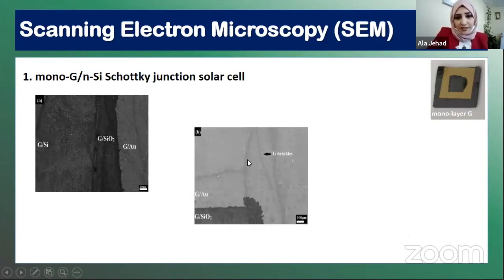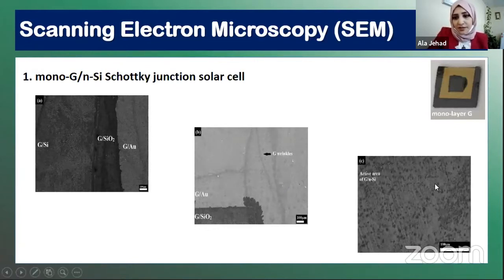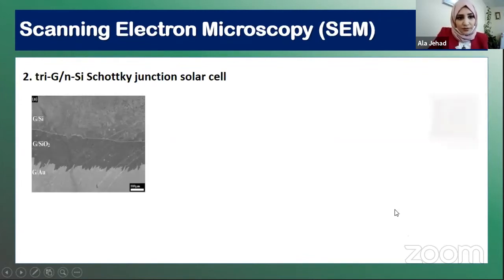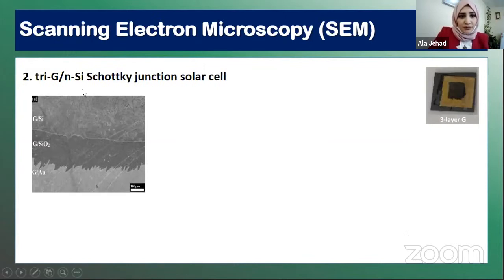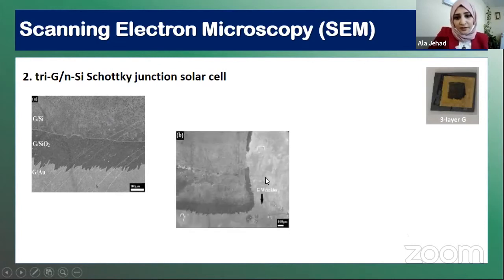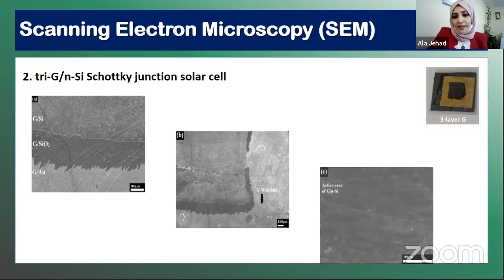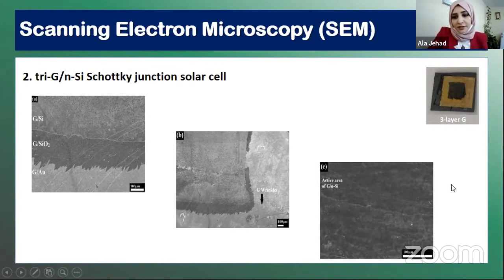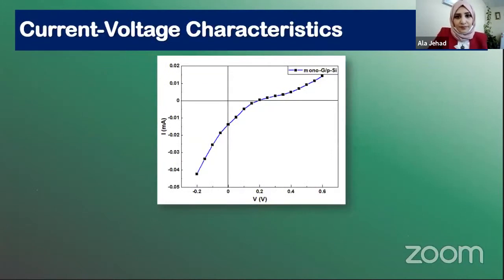Here the same, but we can see the wrinkles of the graphene on the same image. The third was only SEM on the active area. It's the same points we noticed in the microscope when we used it. And here for the second, when we transfer 3 layers of the graphene, we still can distinguish layers like metal, silicon dioxide, and silicon. And the wrinkles are more clear in this case because we transfer the graphene three times. And here we have the active layer, and we can see it's more dark and with lots of PMMA residue.